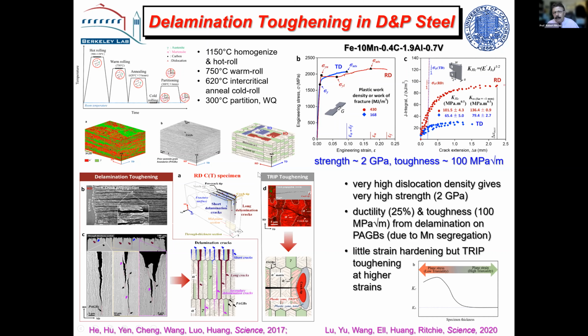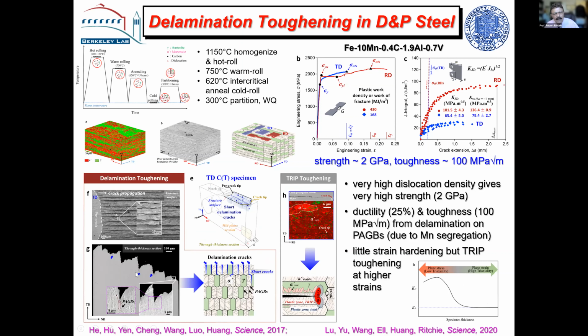So the short transverse properties of this steel would be very bad, but when it breaks with the crack divider orientation, we get this very, very high toughness. We get a series of these plane stress regions rather than one plane strain region. Very interesting phenomenon. You can see these delaminations exactly the same way as the aluminum lithium alloy.